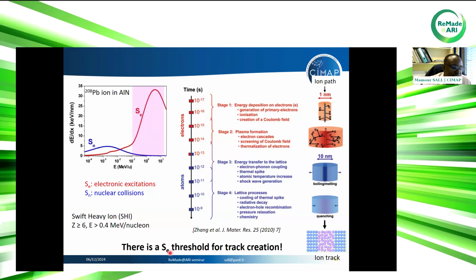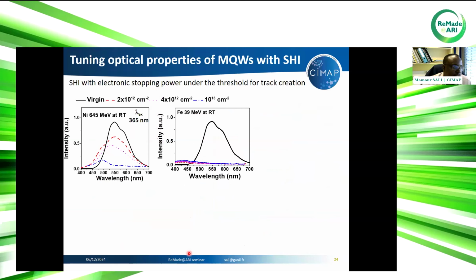So this means that there is an electronic stopping power threshold for track creation. For the following, we will use ions with electronic stopping power under the threshold for track creation. In fact, what we want is to modify the material by ionizing radiation without creating the tracks, because we know that the tracks are defects that can quench the luminescence of the multi-quantum well. So for the following, all the irradiation was done with swift ions without tracks.